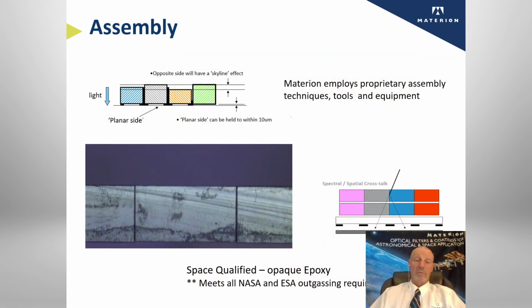Typically what we want to try to do is maintain 10 micron coplanarity on the detector side. What that does is that gives a skyline effect on the backside. The skyline effect is usually in the range of 20 microns or so. Now, if somebody really needed a coplanar on both sides, we can and have done that before. It just adds a few steps and some complexity to the assembly process.